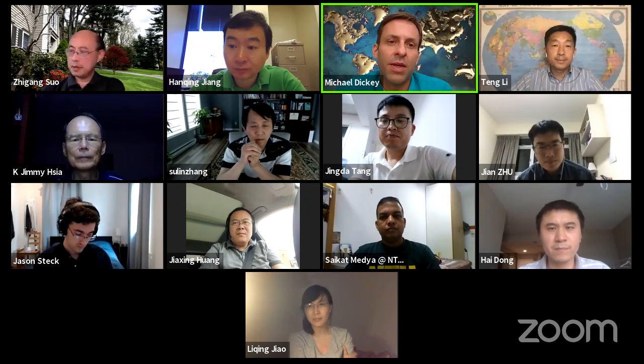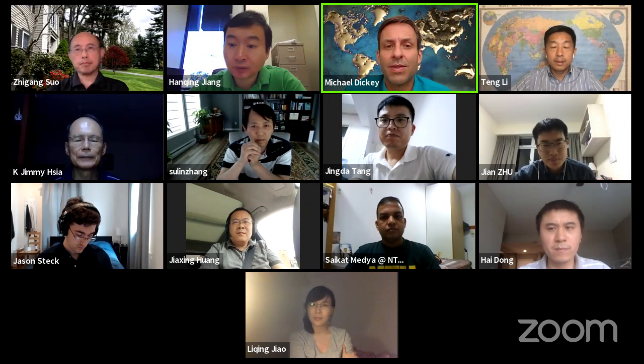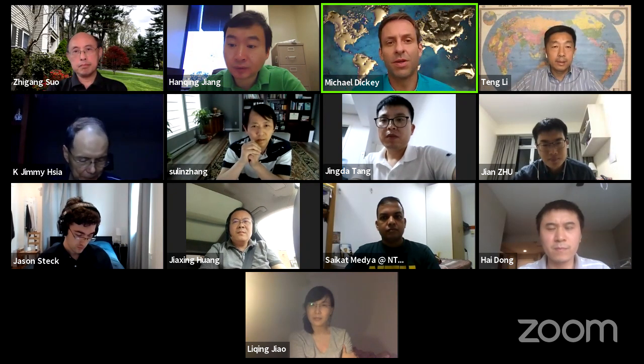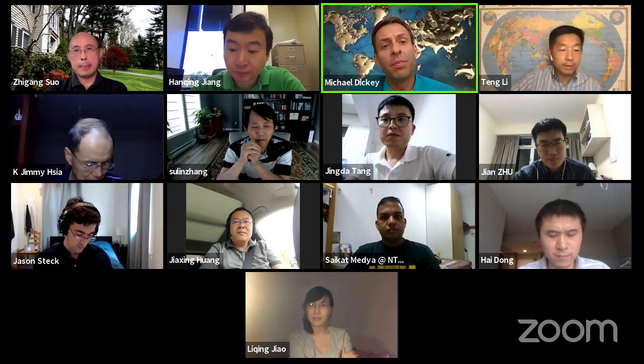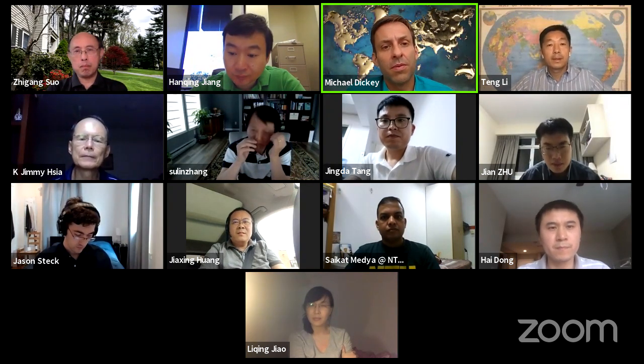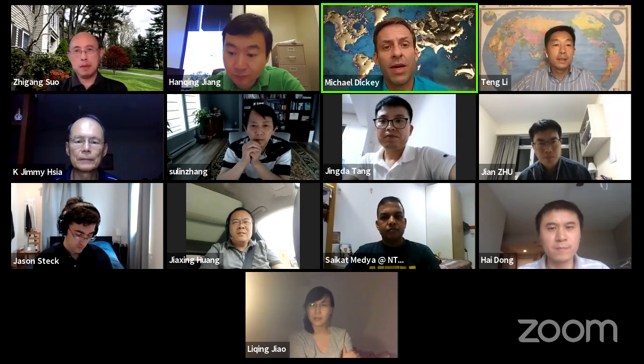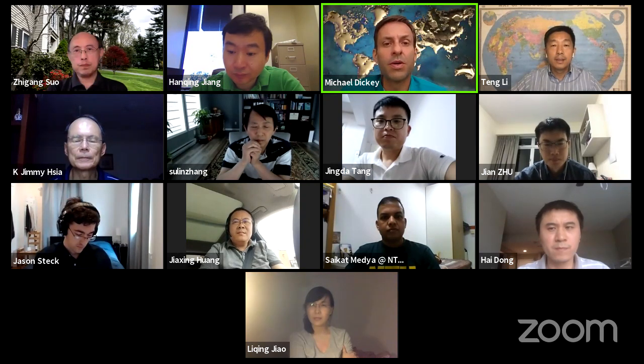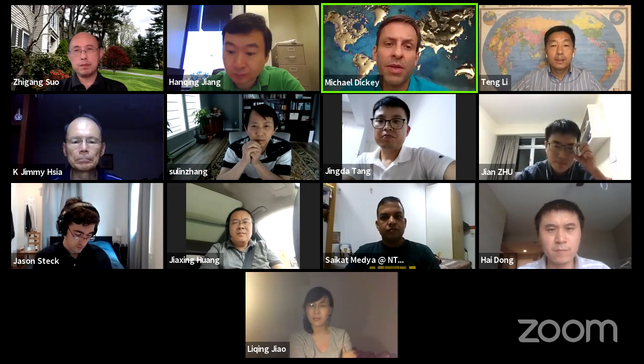Most of the work that's in the literature is looking at grafting stuff to the oxide itself. So you have the oxide and then form an additional shell around it to change the chemical functional groups and that kind of thing. And in that sense, it's not surprising. It's an oxide, you can do silane reactions and that kind of thing. But you might imagine that if you sonicate the metal in thiol, thiols are known to bond to metals very strongly. And there has been some work in that regard to use thiols to bond to the metal surface.